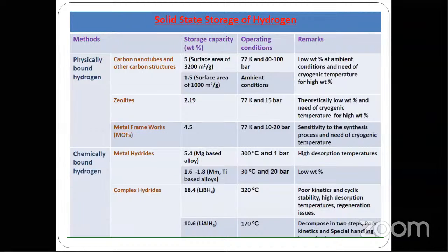And for low temperature applications, we can use metal hydrides like MM-based, misch metal-based alloys or titanium-based alloys. You can store easily 1.6 to 1.8%. And the advantage is that the operating conditions are near to the atmosphere, like 30 degrees and 20 bar. The only drawback is low weight percentage compared to our target, but still we can use them for transport applications safely. And from the energy point of view, those are the best materials to store the hydrogen for transport applications.